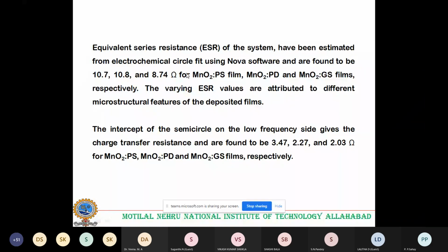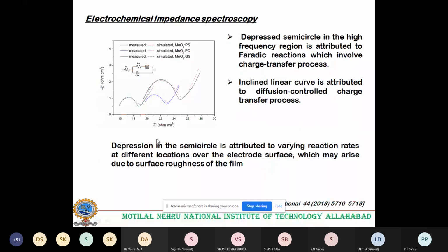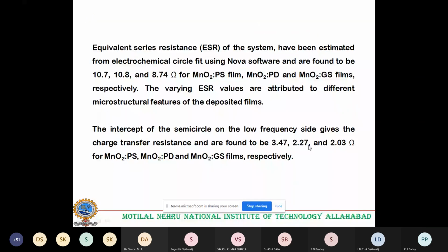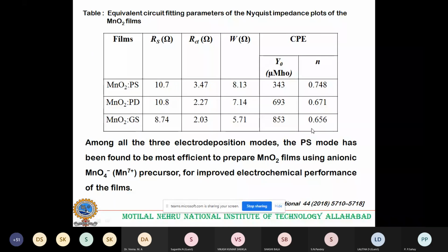We have calculated the equivalent series resistance of the systems for the three different cases, and we got these results. The varying ESR values are attributed to the different microstructural features of the film. The intercept of the semicircle on the low frequency side will give the charge transfer resistance. That we calculated, and it comes to be 3.47 and so on. This is your table. The same thing I have summarized: the series resistance, the charge transfer resistance, the Warburg diffusion, and the constant phase element. All these have come from your electrochemical impedance spectroscopy.